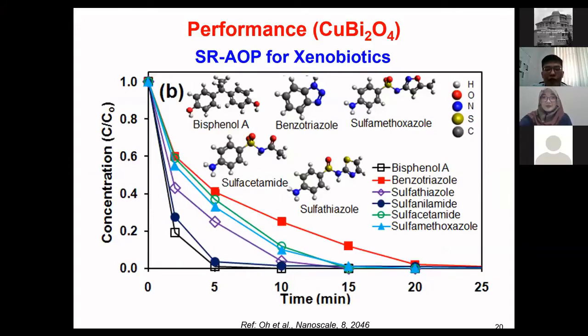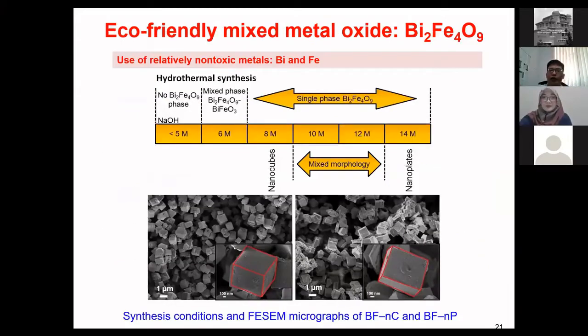But before that, just to share with you, this catalyst is very versatile in the sense that it can be used to remove not only benzotriazole, you can also use it for other xenobiotics, for example, bisphenol A, sulfacetamide, and so on. And to improve further on copper bismuth oxide, the next thing that we want to do is to remove copper completely. Because we found that even if we manage to reduce the copper leaching to 0.01 milligram per liter, that will still be a problem to the environment.